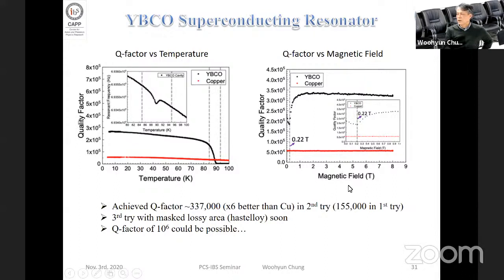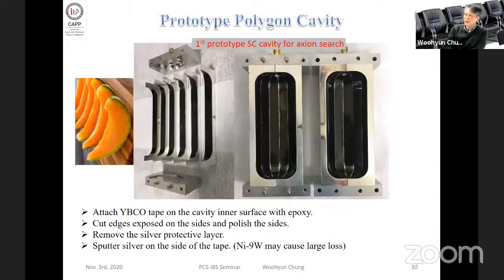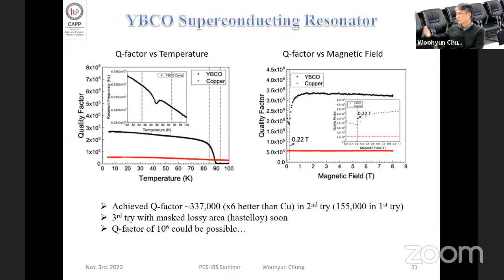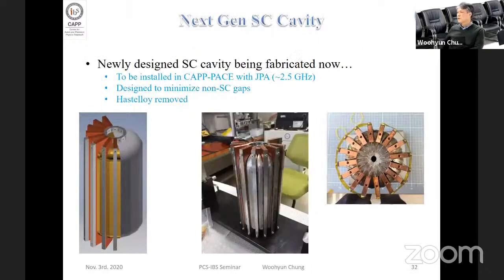The real test is when you put it into a magnetic field of up to 8 Tesla, and it jumps up and then stays. That means we can use it up to 8 Tesla. If you look at the previous picture again, it has many gaps between tapes. That's probably why we couldn't reach a million Q factor, because of those gaps. So we'd like to improve it and minimize those gaps.